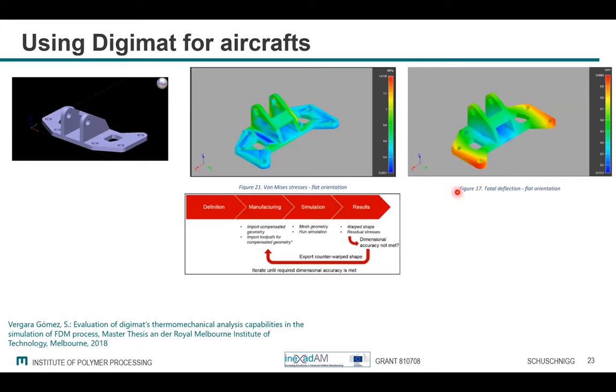If I make these definitions, I go from the flat part to the results, to the deflection, and then I take this deflection and multiply it by -1. So I have an inverse deflection, and then I go back to the manufacturing simulation, and then I have a deformed original part. Then I print this deformed part and the warpage will work against it. Mostly you have to do it in an iterative way to get, after the final simulations, the good contacts out of it.